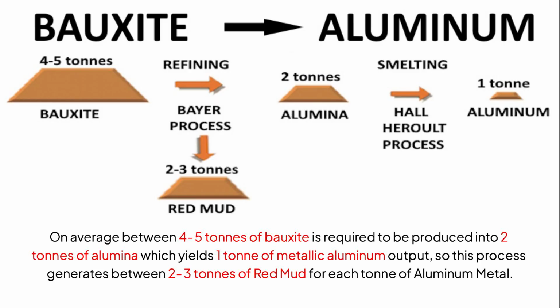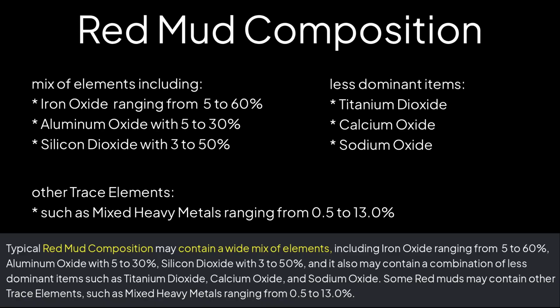On average, between 4 to 5 tons of bauxite is required to be produced into 2 tons of alumina, which yields 1 ton of metallic aluminum output, so this process generates between 2 to 3 tons of red mud for each ton of aluminum metal. Typical red mud composition may contain a wide mix of elements, including iron oxide ranging from 5 to 60%, aluminum oxide with 5 to 30%, silicon dioxide with 3 to 50%, and it also may contain a combination of less dominant items such as titanium dioxide, calcium oxide, and sodium oxide. Some red muds may contain other trace elements, such as mixed heavy metals ranging from 0.5 to 13.0%.